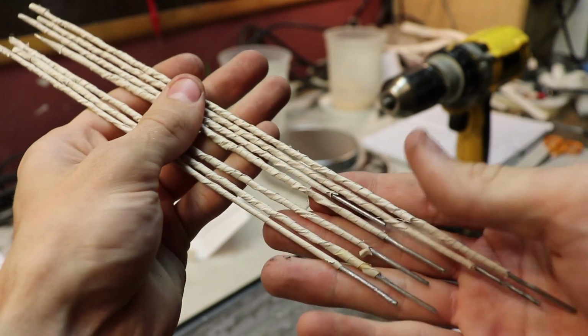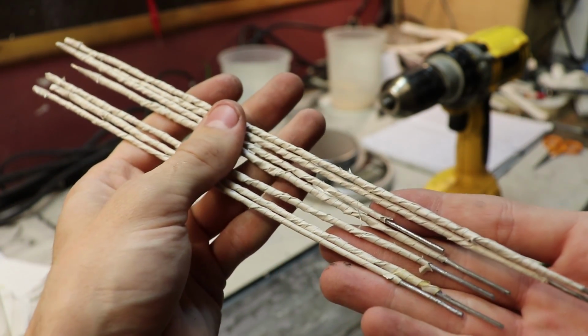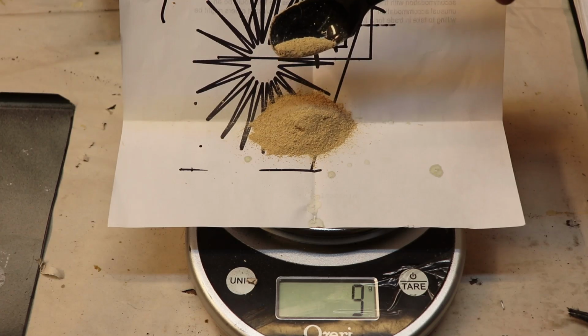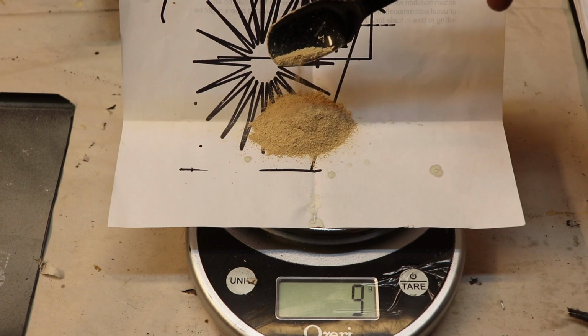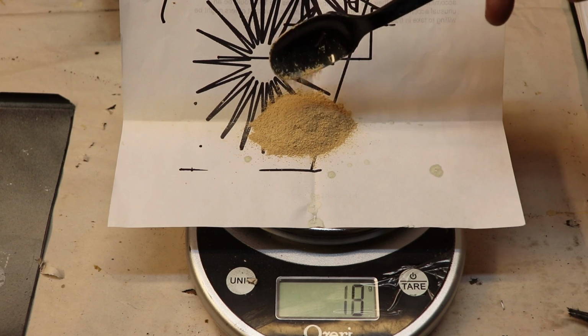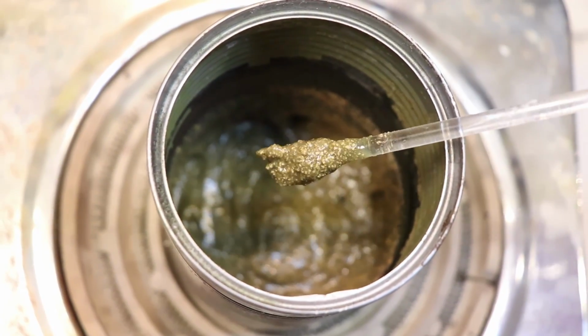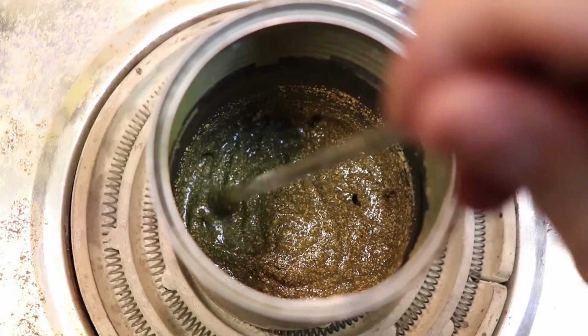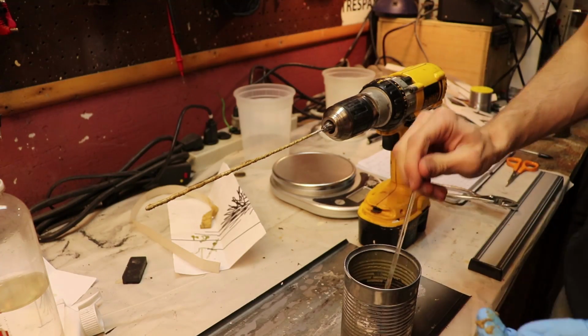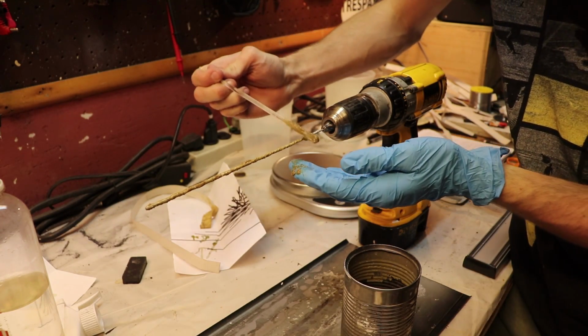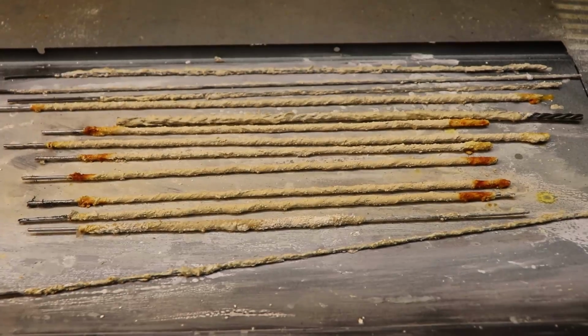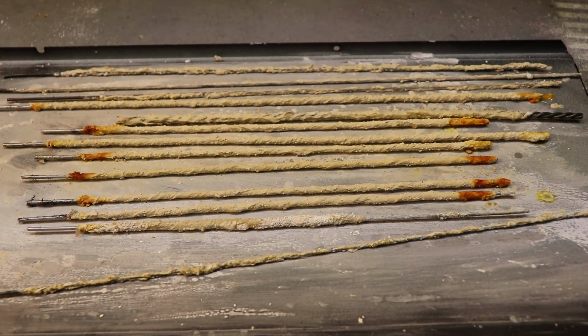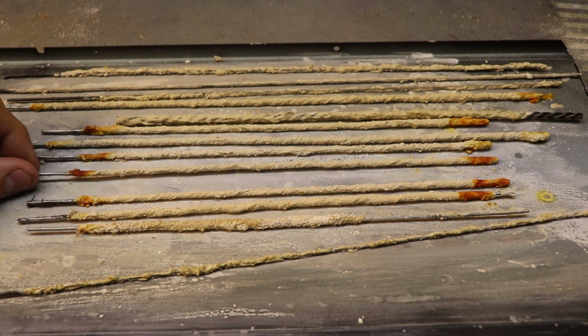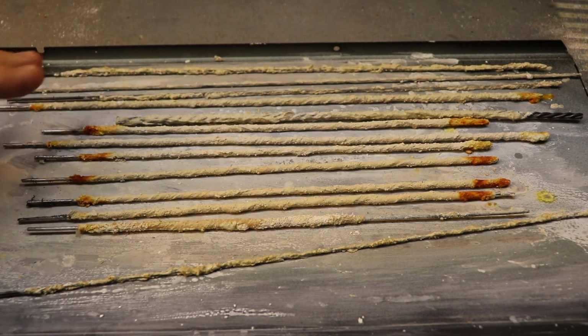Now I went back to making more rods, wrapping all of them correctly this time and adding 10 grams of calcium carbonate we prepared earlier, which when mixed in the solution looked like this. It thickened up instantly, and now I could coat the rods using a glass stirring rod instead of a glass dropper. After baking the rods, this is what they looked like. So I just took these rods out of the oven and they're completely bone dry.